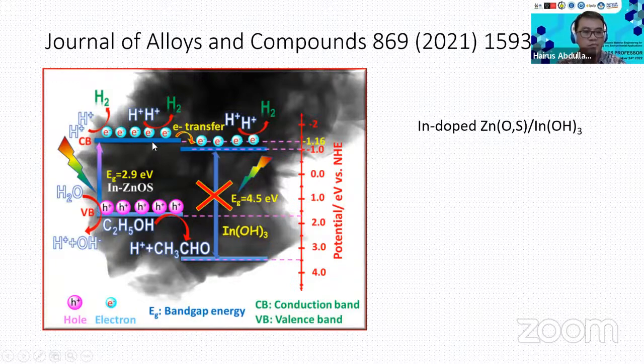Because the conduction band position of the indium hydroxide is suitable for electron transfer, this helps to reduce the recombination rate between electron and hole, right? The electron moves from the indium doped ZnOS to the other indium hydroxide phase. Once the electron moves to the other phase, the hole still stays in the indium doped ZnOS phase. This will improve the charge separation, right? Because they are now in different phases, the possibility of recombination becomes lower. So that's the concept, and it is very interesting for this work.